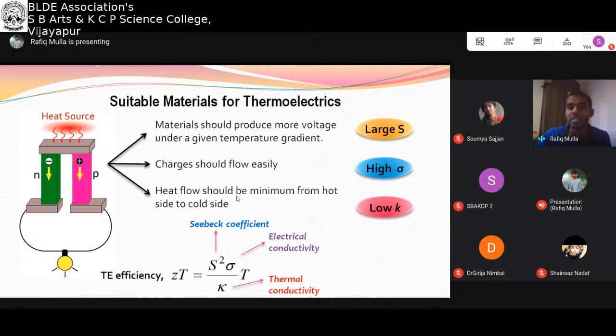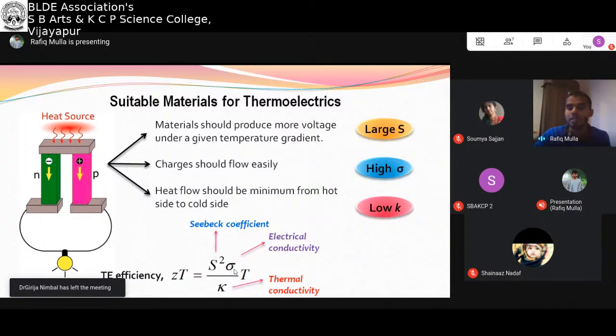So materials which control the heat flow from hot side to cold side are important for this kind of applications. So what these points mean is we need large Seebeck coefficient, that is already as we defined, delta V by delta T, large S, and we need better electrical conductivity, but at the same time we need very low thermal conductivity. In fact, this is very clear from the standard expression of thermoelectric efficiency that is defined as ZT. It is given by S square sigma divided by K into T, where T is the average temperature of the device. So S is Seebeck coefficient, sigma is electrical conductivity, K is thermal conductivity. So S and sigma are in the numerator, and K is in the denominator. We need better values of S and sigma, and that's why we must need low K value to have better ZT value. So better ZT value means better efficiency of the devices, and materials which have better ZT value are suitable for the thermoelectric applications.